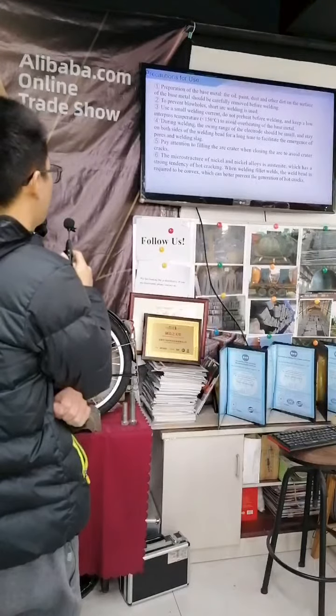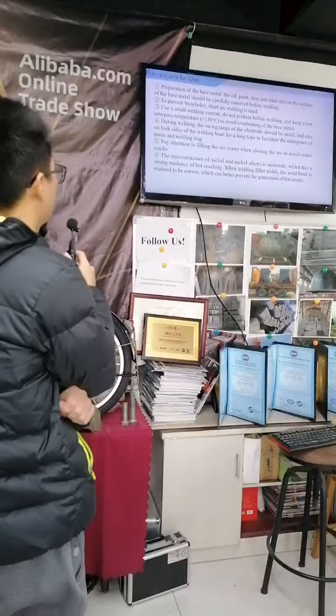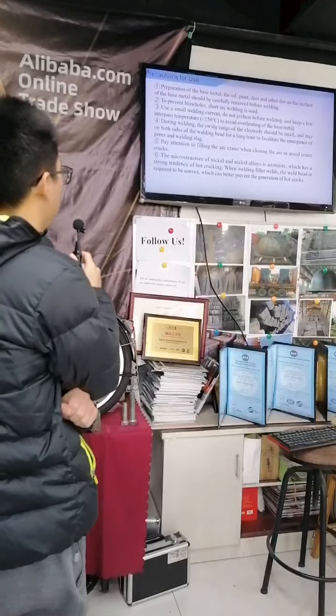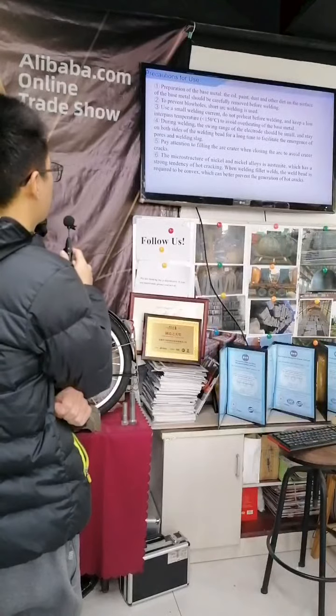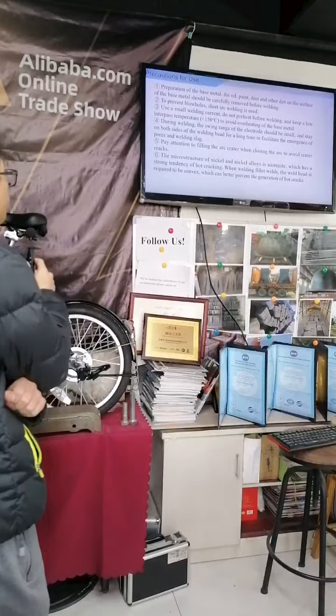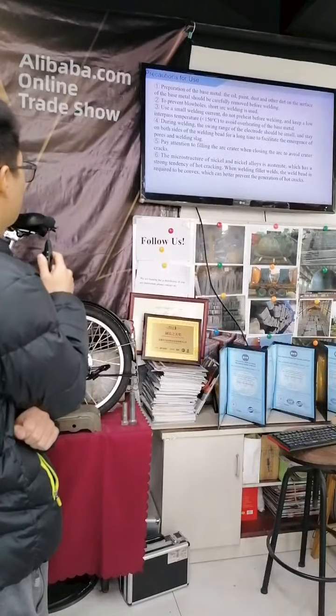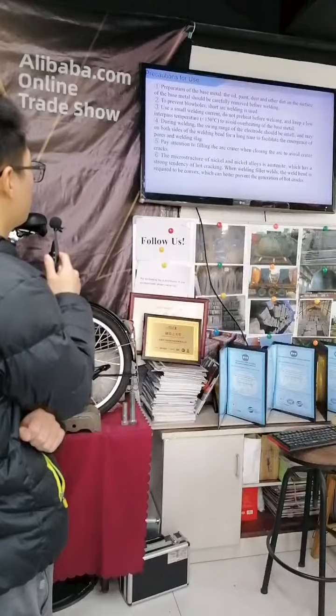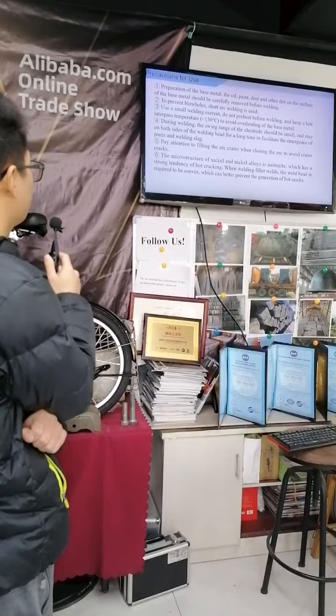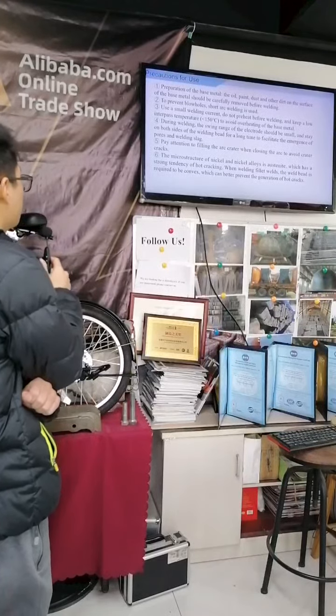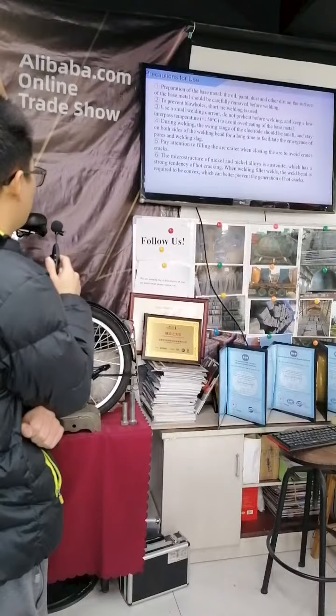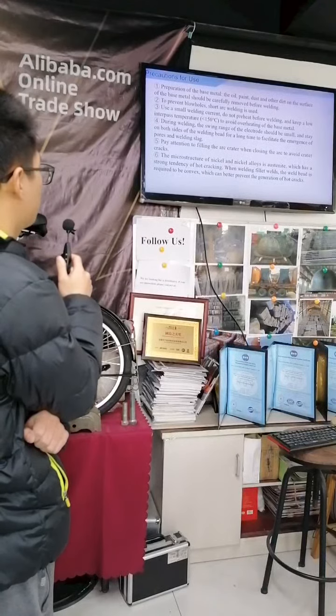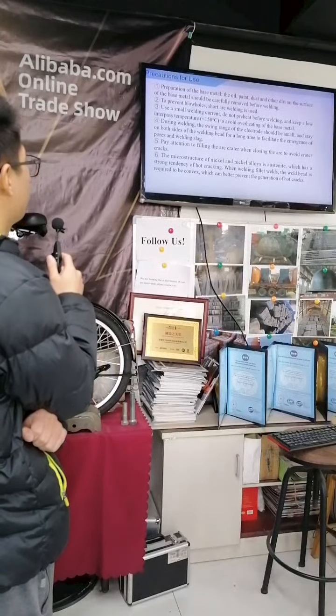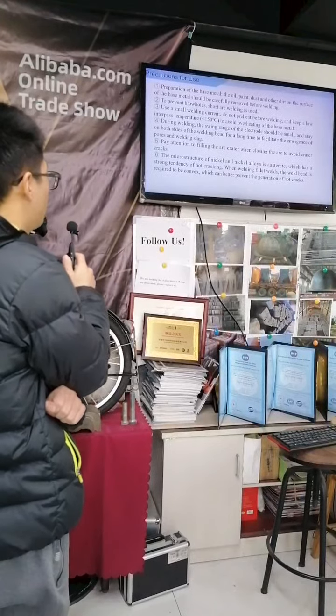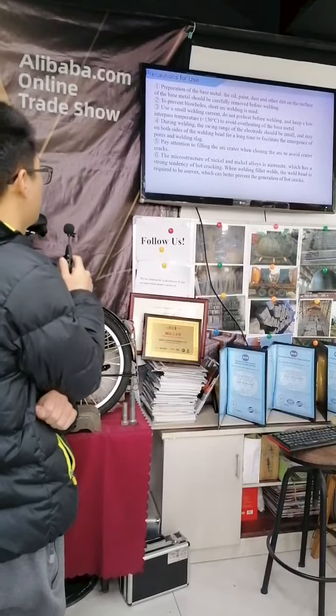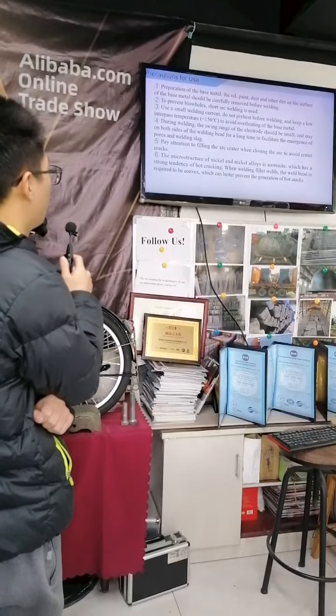During the welding, the swing range of the electrode should be small, and do not stay on both sides of the weld for a long time, to facilitate the emergence of pores and welding slag. You should also pay attention to filling the arc crater when closing the arc to avoid crater cracks. The last precaution is that the microstructure of nickel and nickel alloys is austenite, which has a strong tendency of hot cracking. When welding fillet welds, the weld is required to be convex, which can better prevent the generation of hot cracks.